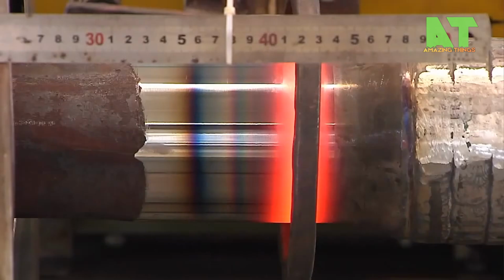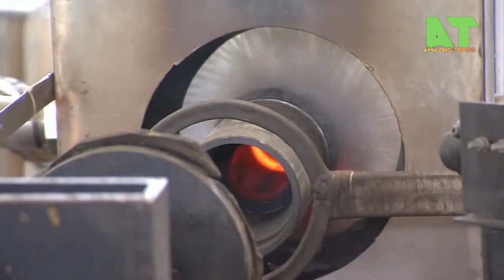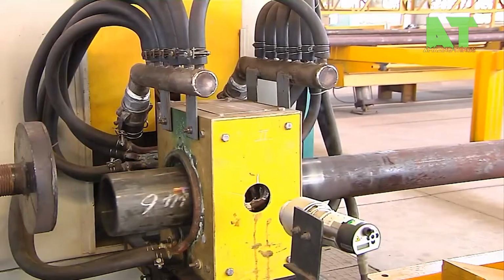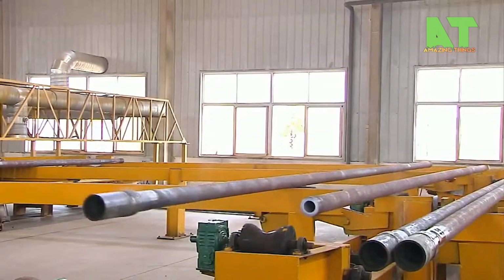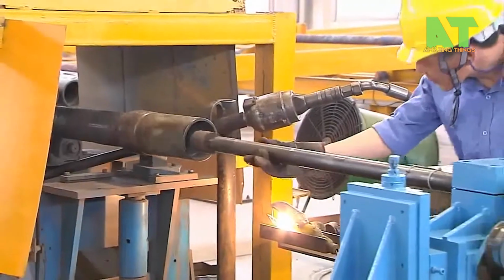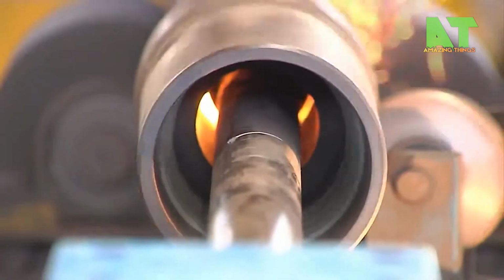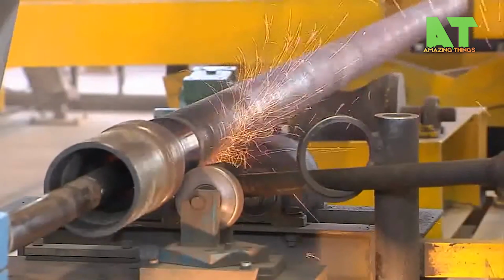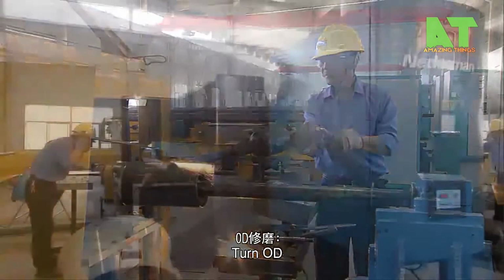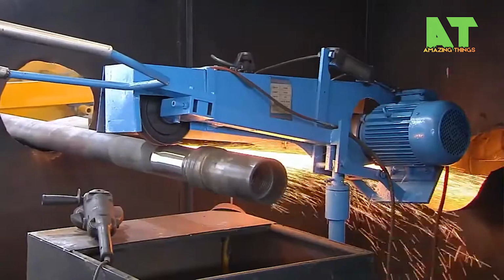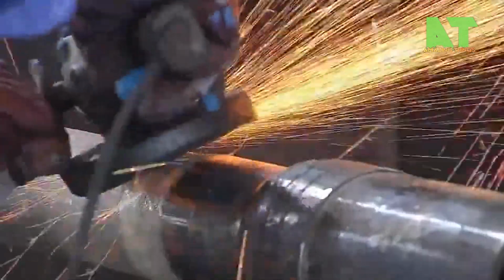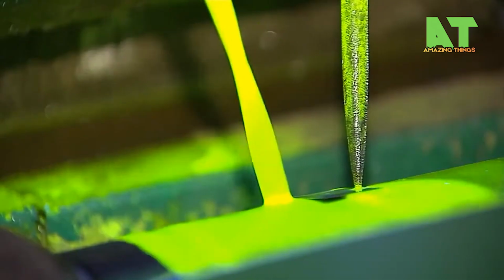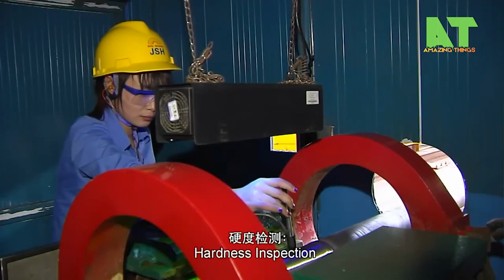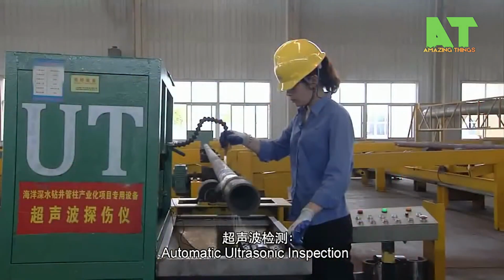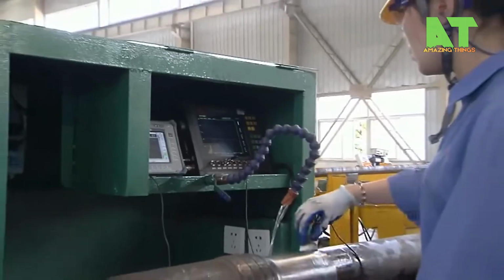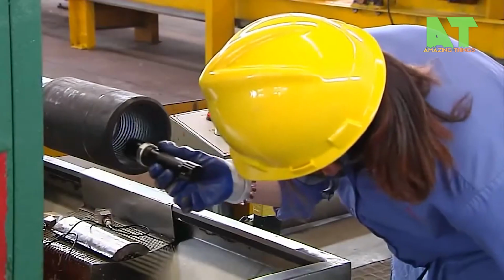Joints are then friction welded to the pipe body, a process that generates heat through rotation and axial pressure, creating a metallurgically bonded joint without filler metal. After welding, the joint area is inspected by magnetic particle testing and ultrasonic methods to confirm weld integrity. The completed pipe is then full-body ultrasonically tested, hydrostatically pressure tested, and measured for straightness before receiving its final coating, typically a zinc-based internal lining for corrosion resistance and flow efficiency.